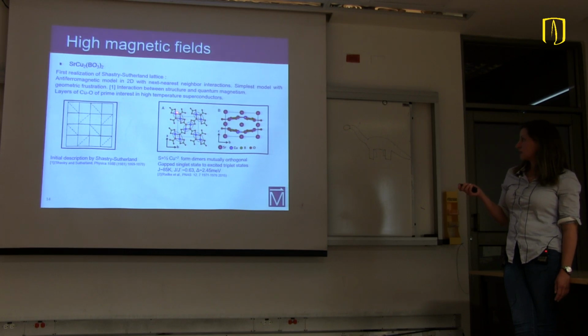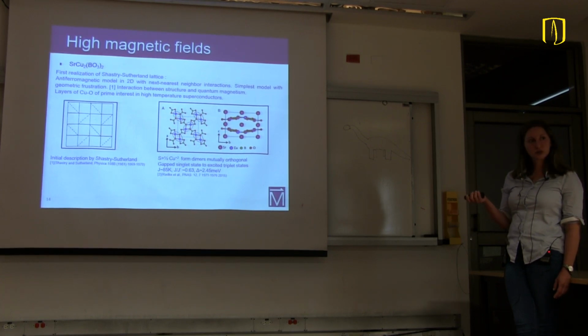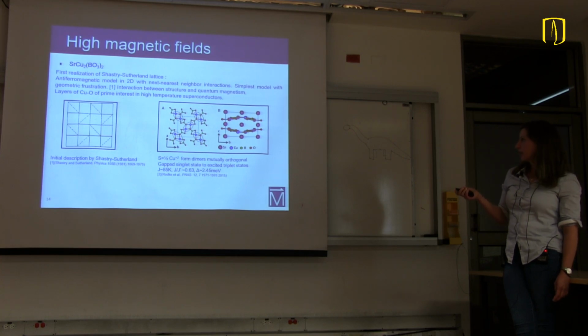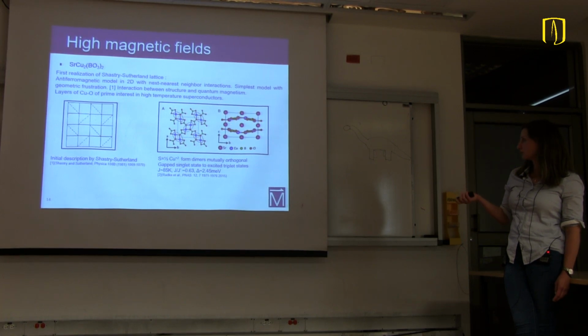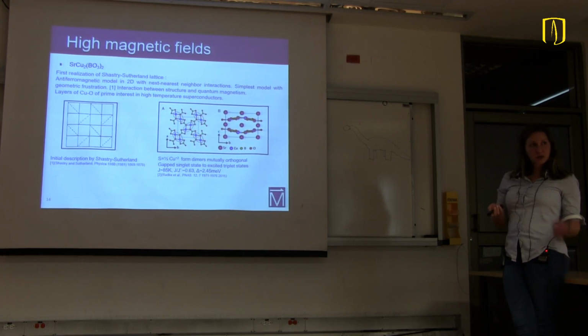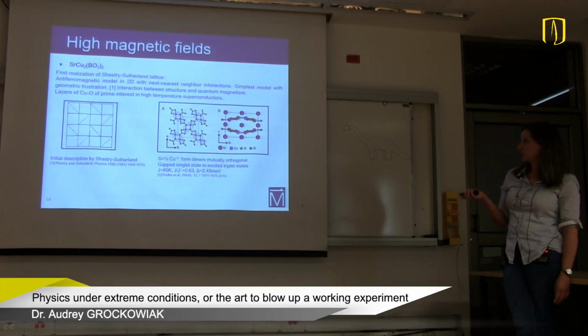So this is the structure of this sample. The blue atoms here are the copper atoms. They're organized in pairs, called dimers. And those dimers here are orthogonal to each other. And so this is the creation of the frustrated magnet here. And they form layers, this layer here, separated by strontium atoms. So this discovery triggered a lot of experimental work.